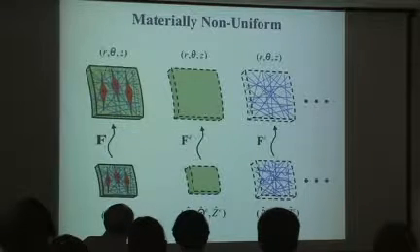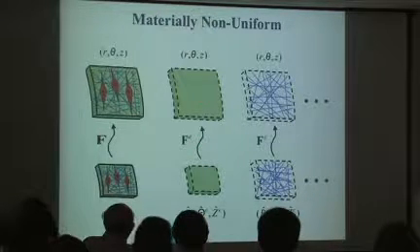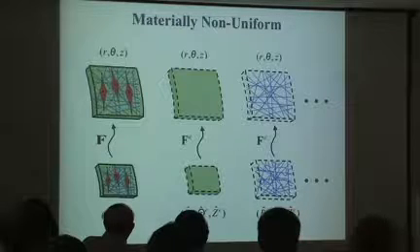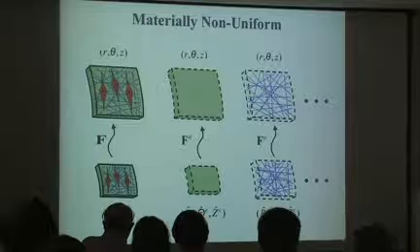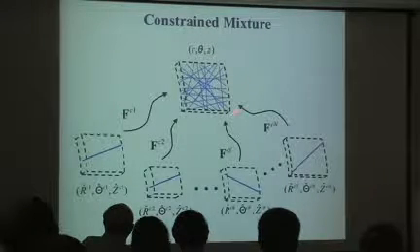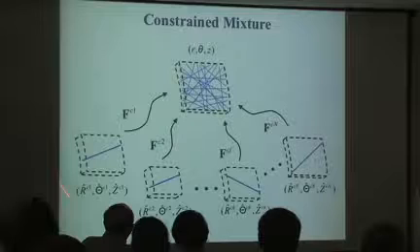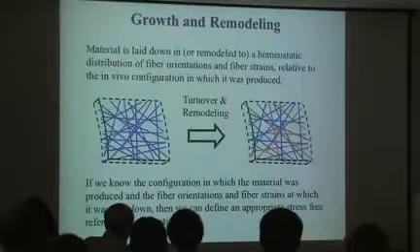But these constituents can possess their own stress-free or natural configurations, which are key when we're performing stress analysis, because we need to identify the stress-free configuration before we can map this to calculate the stress. And indeed, individual constituents here, for example, different collagen fibers, can have different stress-free configurations. And so collectively, the strains in the different fibers can be different.